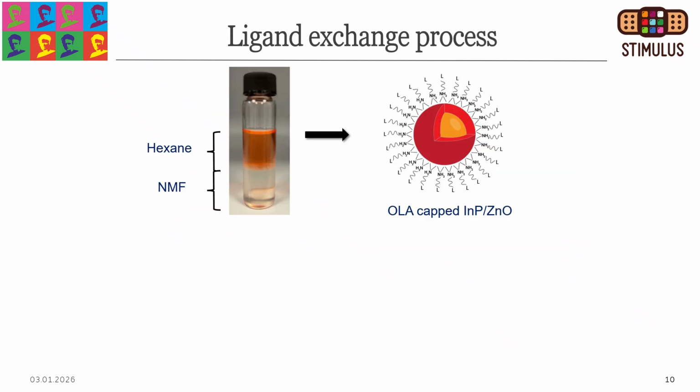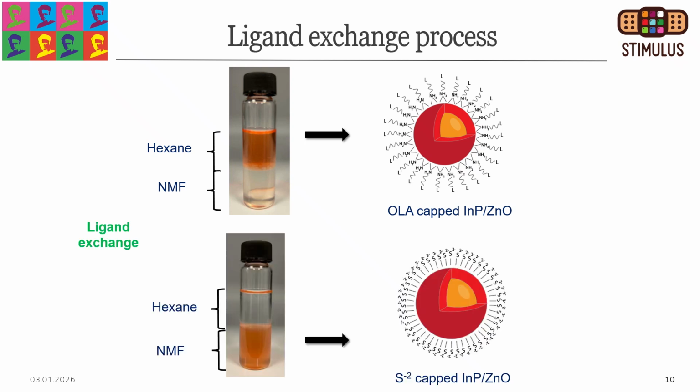Ligand exchange process. When we synthesized these quantum dots, they were capped with oleylamine, and due to this oleylamine capping, they were only soluble in non-polar solvents such as hexane. We cannot use these quantum dots for biological applications because for biological applications, the quantum dot should be soluble in water. For this purpose, we replace the oleylamine ligands with the sulfide ligand.